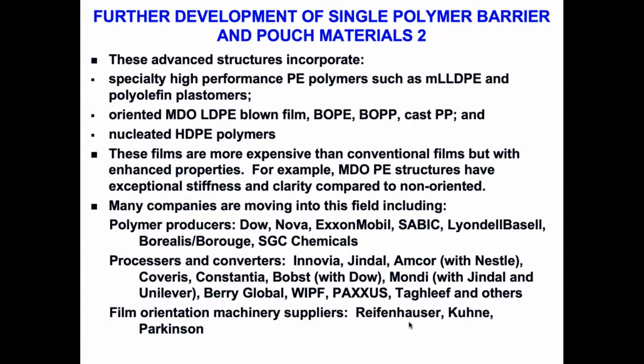Oriented films can be MDO LDPE blown film, biaxially oriented polyethylene or polypropylene, cast polypropylene, and also nucleated high density polyethylene. These films are more expensive than conventional films, but they give all of the enhanced properties I've just mentioned. For example, the machine direction oriented PE structures have exceptional stiffness and clarity.